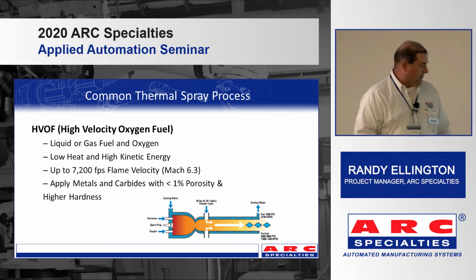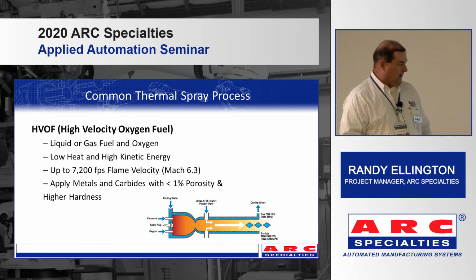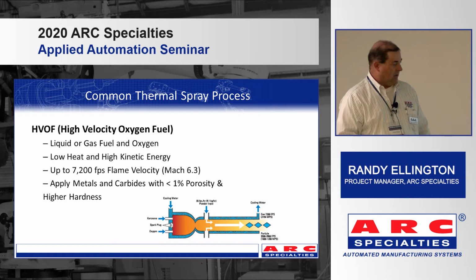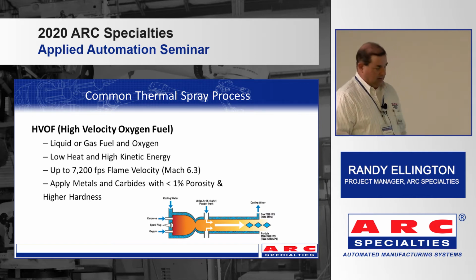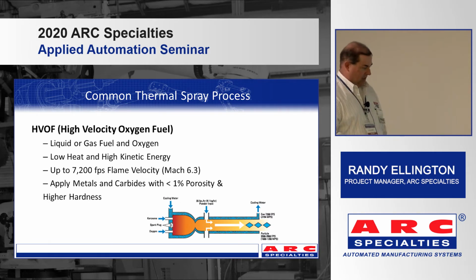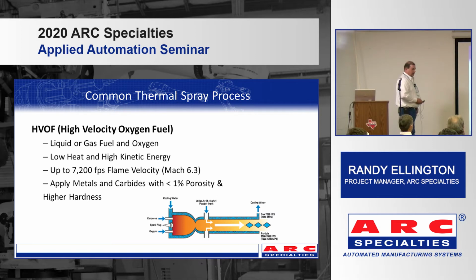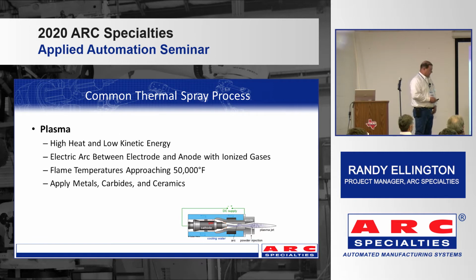The process is usually used for just basic metals and carbides. Like I said, less than 1% porosity, high hardness. With the carbides, it's not uncommon to see 1,200 DPH, 300 gram load hardness, so it's pretty dense.